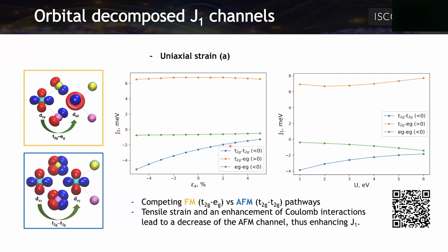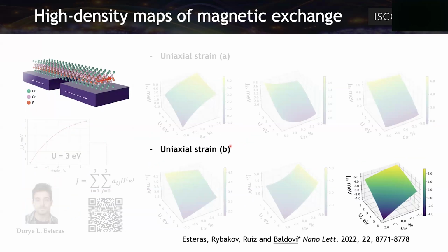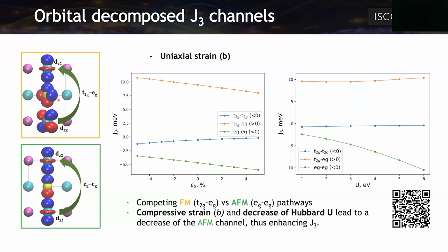Regarding the other strain that we apply in the calculations along B, in this case, this is in the direction of J3. So we can observe here that J3 is increasing when we are, this is negative, so this is compressing the material. So we have now the opposite trend. And in this case, there are these two mechanisms. This is the ferromagnetic one, coming from a t2g orbital to an eg, from the dxz to the dz squared. And this is increasing when we are compressing the material. And on the other hand, this eg path is also being decreased here. So we have at the end that the compression is enhancing the value of J3.